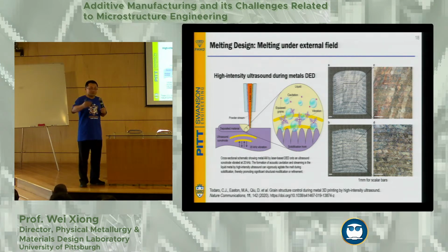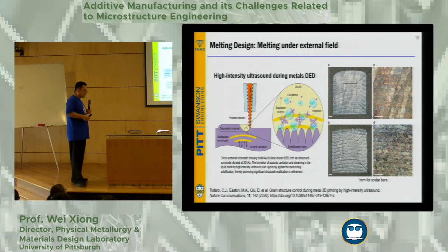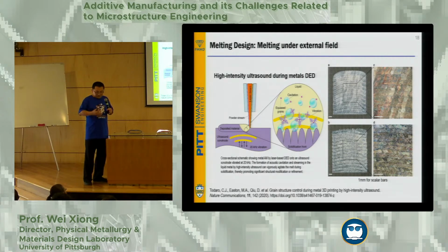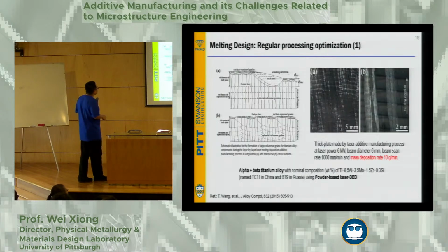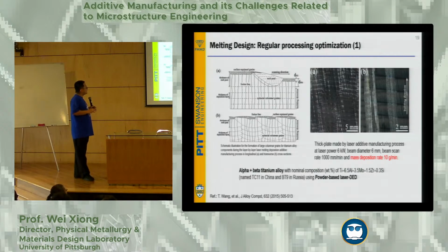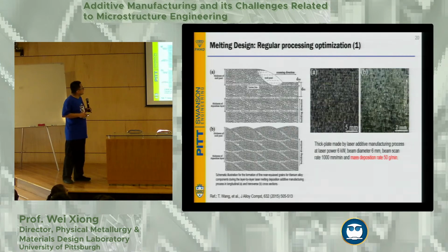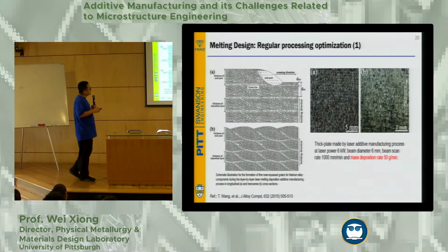All right, I still remember once I went to Chinese Academy of Science in Shenyang, and then they were using some magnetic field to making sure the homogeneity of the melting of the button alloys. That's actually also applicable. And the other thing is like, if you can understand quite well with the processing itself, then you also have a lot of opportunities to change directly during the melting process, okay? So that's one of the studies regarding the titanium alloy. If you look in detail, this is kind of the sketch, however, is more or less similar as you see the microstructure with the wire printing.